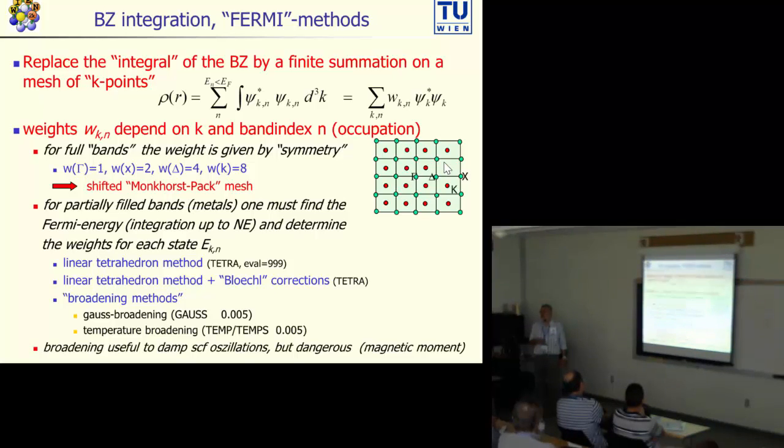If I want to simulate a surface or a graphene sheet, a single sheet, right? So if I want to simulate a 2-dimensional material, then my Brillouin integration is effectively only a 2-dimensional integration, not a 3-dimensional one. And if you form tetrahedra on a 2-dimensional system, they are all triangles, they are all degenerate, and that can lead to problems with the tetrahedron method.